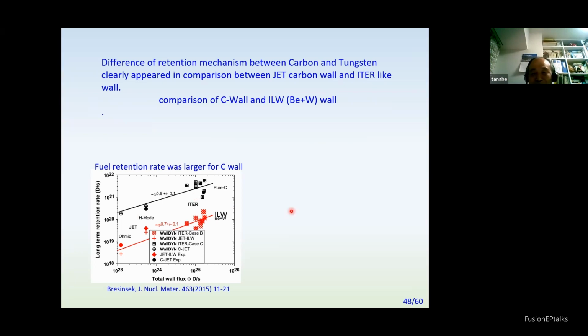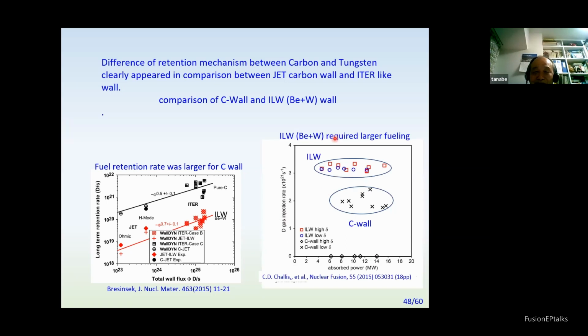But interesting is the fueling - in case of ITER-like wall, they require larger fueling compared to carbon, which means that ITER-like wall takes a lot of hydrogen during the shot, but it's released afterward. So that comes down smaller in the retention. In the carbon case, this is several times, I told you 3% something, but going to the tungsten case, this becomes 0.3%. So there are large differences in the characteristics of hydrogen retention.